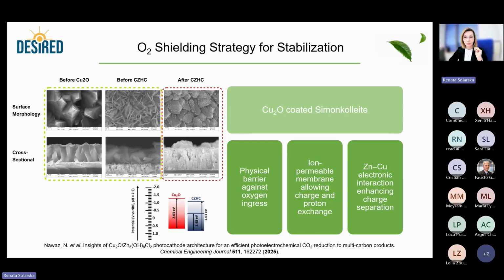And you can see on the SEM picture, this is a very good contact, which allows us to not only protect the electrode against photocorrosion, but also to create a physical barrier against oxygen, while at the same time allowing charge and proton exchange, so it can work effectively in the photoelectrochemical environment. In addition, the zinc hydroxychloride forms a direct contact with the copper oxide. So in the electrolyte, it suppresses the photocorrosion while maintaining the charge mobility.